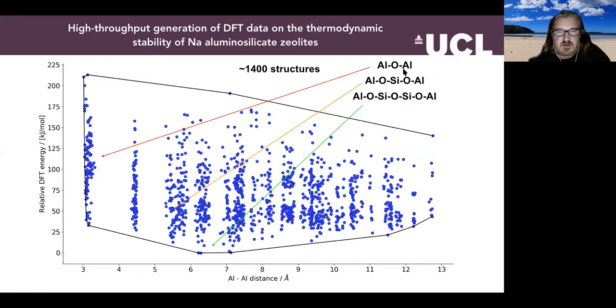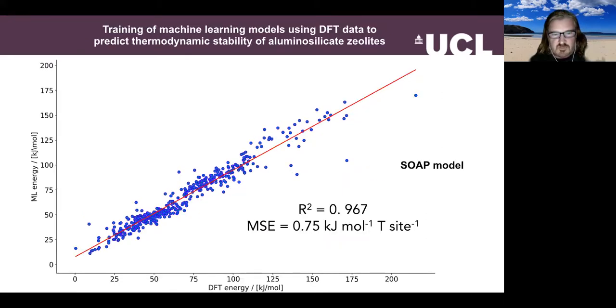Now this is fine, but it costs a lot of compute time. It turns out that the real catalytic materials are extremely complex in terms of composition, crystallography, and symmetry. So we can't use brute force DFT to evaluate all of the possible configurations for some of the more industrially relevant materials. Hence we've been looking towards, again, machine learning. This is the SOAP model, which we heard about a few weeks ago from Professor Csányi in Cambridge. Here we've taken a subset of the data that I just showed you, used it for training, and we produced a very good correlation with a very modest error. So this looks rather promising.